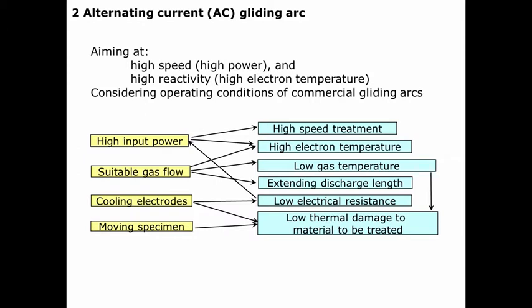Then obviously the electrodes were heated too much. Then it's an obvious solution to try to cool the electrodes. That's why I was cooling the electrodes. But it's interesting to observe that for the gliding arc, not many people, or almost no one, cools electrodes. There are some reasons, but one of them is that there was one literature trying this and then saw some corrosion of the electrodes. Therefore, people probably didn't do that. But for the plasma processing guy, it's quite natural to do that. So that's why I did it.